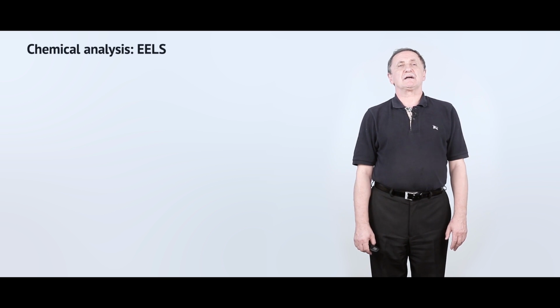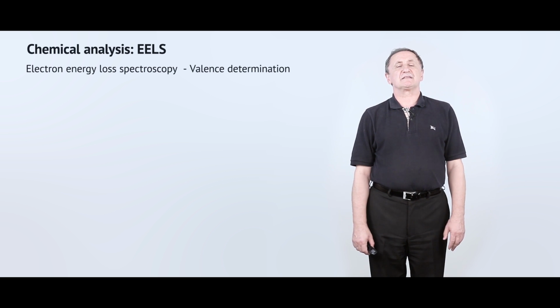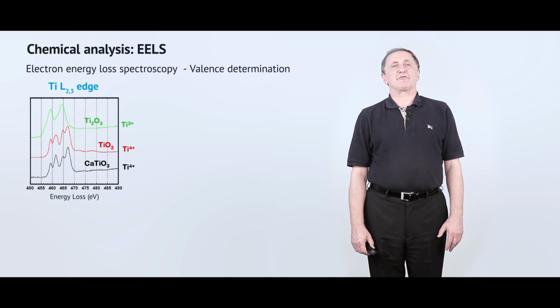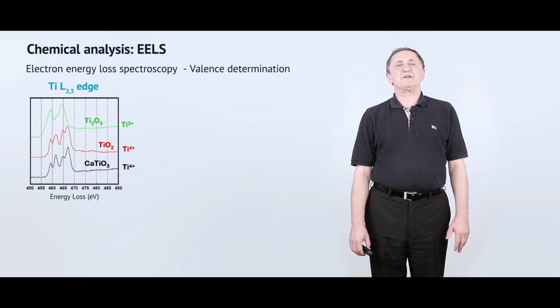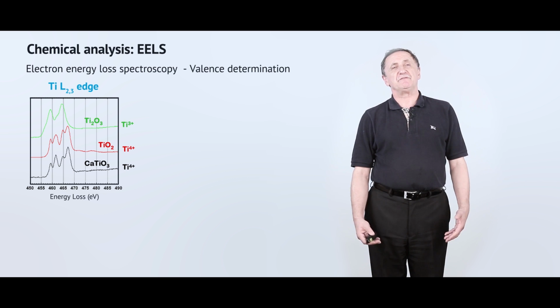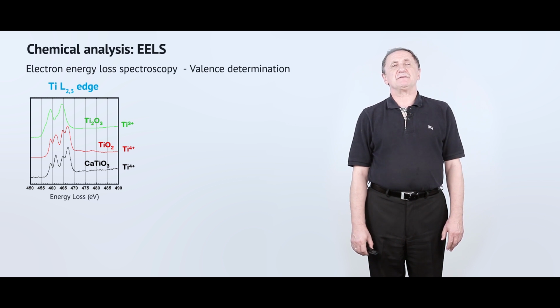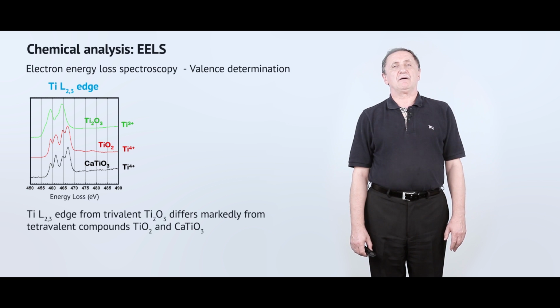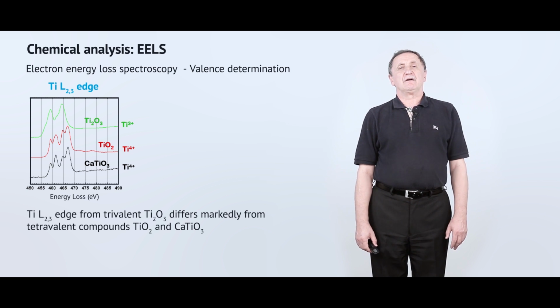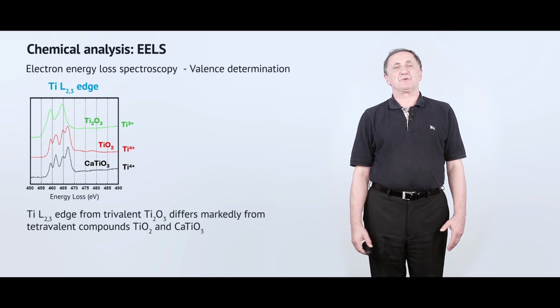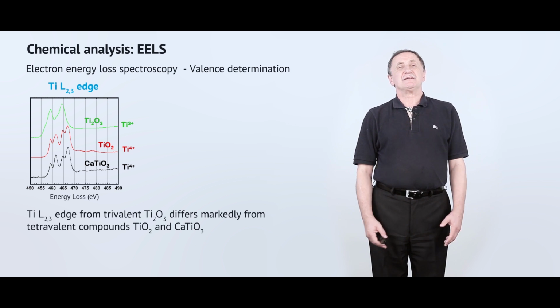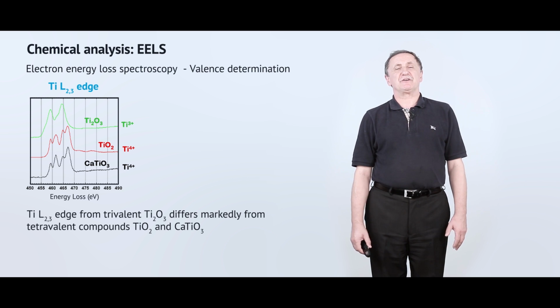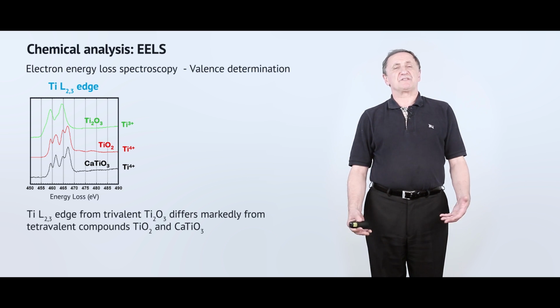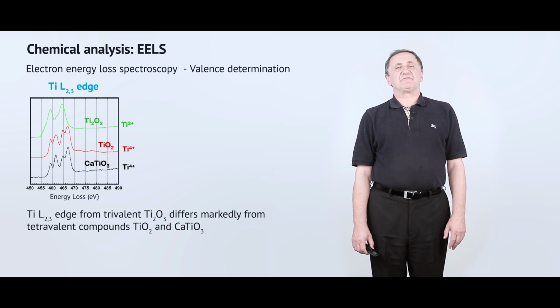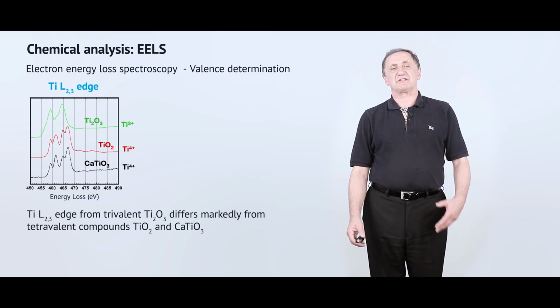So let's conclude. The conclusion is very straightforward. You understand that TEM comprises a range of very different modes, if you wish, which give you a variety of information about the structure of your material. In total, in a modern microscope, you can use 40 different modes, and they will provide slightly different types of information about your materials, which includes imaging, as well as electron diffraction, EELS and EDS spectra, and all together.